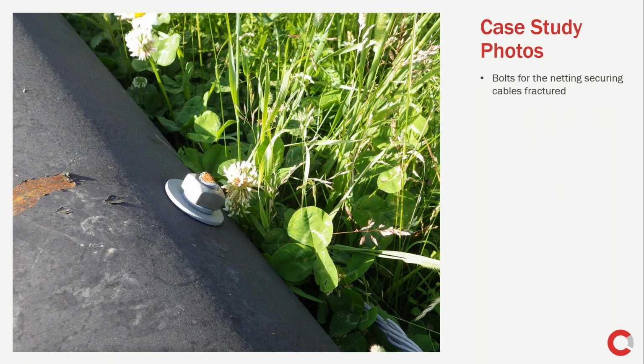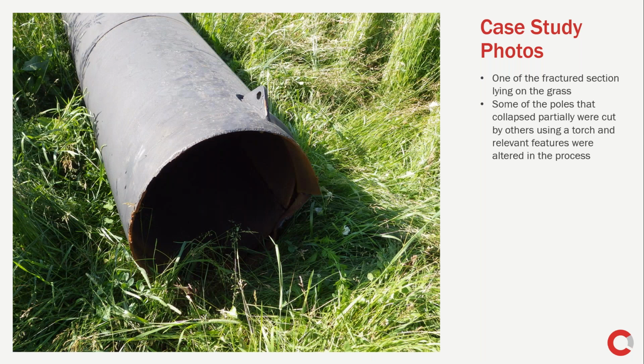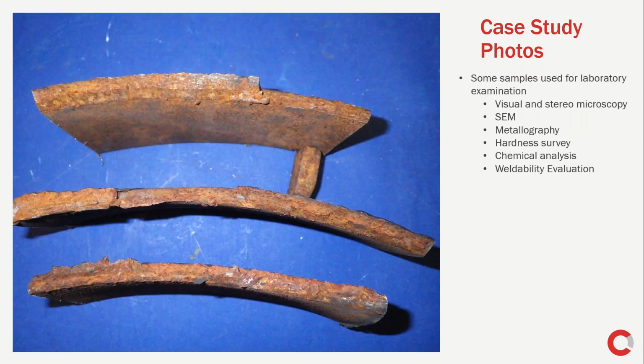This is one bolt holding the netting, and it was also fractured. This is a typical fracture surface from one of the poles. It was a joint examination with other parties, and we jointly selected the samples for further lab examination. The lab examination included visual and stereo microscopy in as-is condition and clean condition, examination of the fracture surface under a scanning electron microscope, metallography to see whether the microstructure is sound, a hardness survey to see whether the heat treatment of the steel was proper, chemical analysis to determine whether the chemistry conforms with the designer specs, and also to check the weldability of the steel.